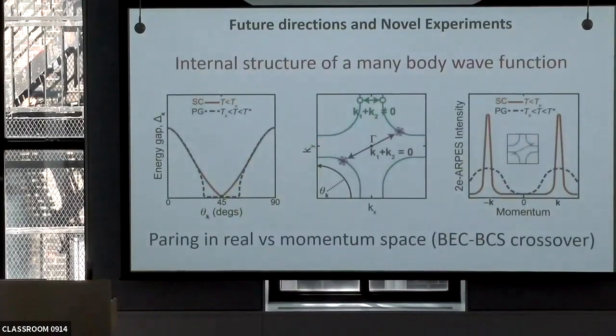So here is a case of a superconducting gap and a pseudogap. In red, as a function of Fermi surface angle, you have a nice d-wave-like gap. You go above Tc, and then you retain a gap at the antinode, and there's no gap close to the nodes. Now I'm working in this superconducting state, and if my Cooper pair has a total momentum of 0, so k and minus k are the momenta of the two electrons forming the Cooper pair, and I do this kind of experiment, I would imagine seeing, when I photoemit two particles at the same time, two electrons coming out, one with a peak at minus k and one with a peak at k. And they should be coming out in a coincidence experiment. So one photon in, two electrons out, and then you explore the angular distribution of those electrons, and you should find two peaks exactly there.